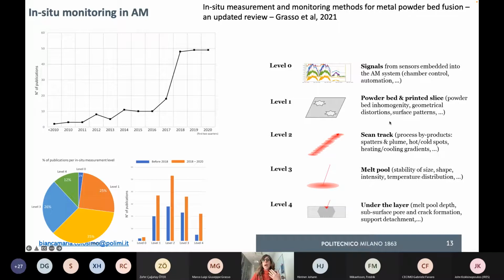You can have information coming out from just the image of the powder bed and the printed slice. You can even go into deeper detail and see what is happening in terms of scan track, if you're focusing on powder bed fusion. And going into deeper detail, you can see the melt pool, just to see how stable the melt pool is in terms of size, shape, intensity, and temperature distribution. And there's a lot of attention now that is rising also in looking beneath the layer you are playing with, trying to see if there's something going on in terms of crack or subsurface pore. I should say that this level number 4 is the most difficult one to be faced with in situ monitoring. Just some examples.